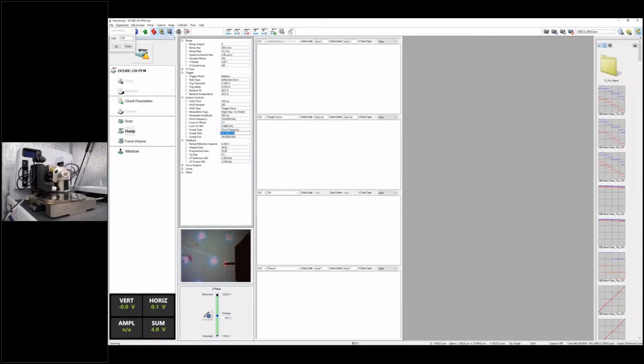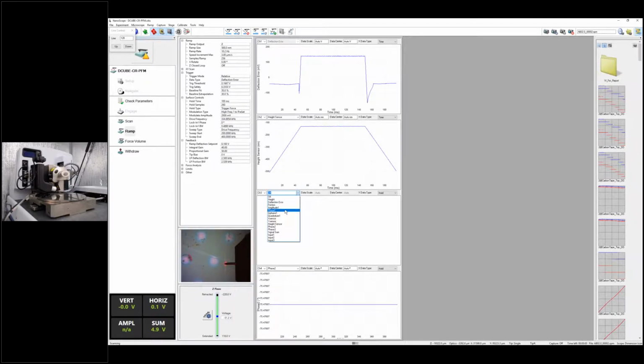I start from 200, give it a relatively wider range, 200 to 400, and increase the drive amplitude a little bit, and want to tune the signal here. Start. Now, if I do a quick test, I can see that when I sweep from 200 kilohertz all the way up to 400 kilohertz, I have a peak around 320, or 320 to 330, somewhere in between. So you already see this peak changed from what we saw earlier, right? So that means within this 320 to 340 window, the frequency will change a little bit.